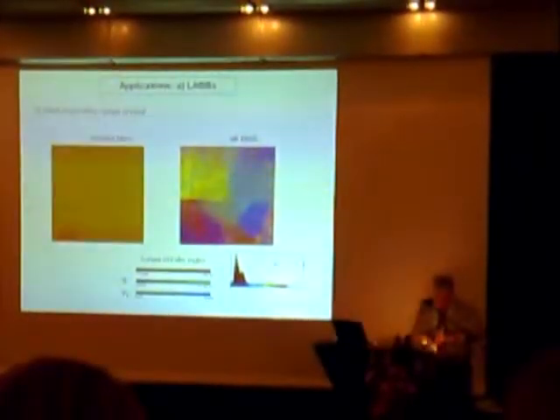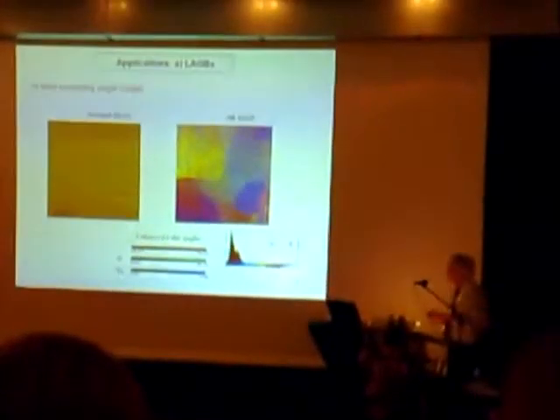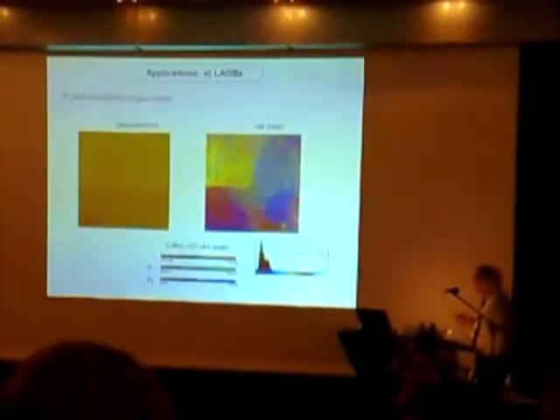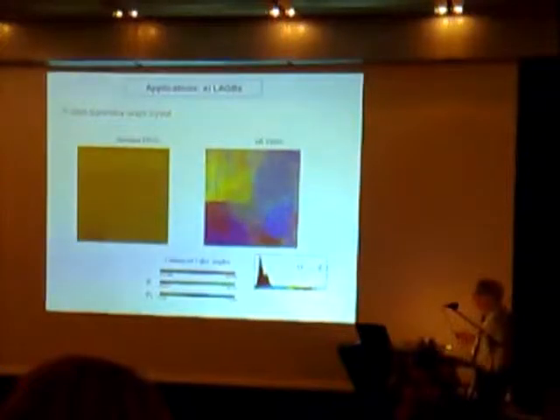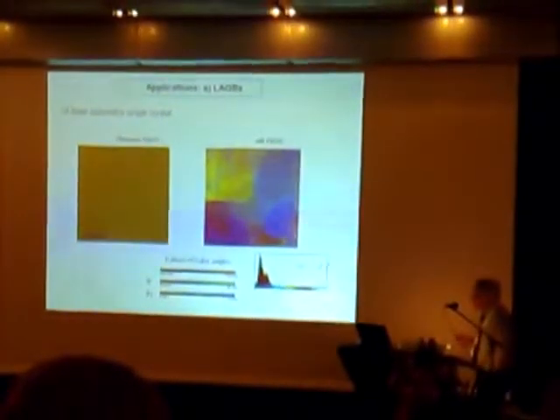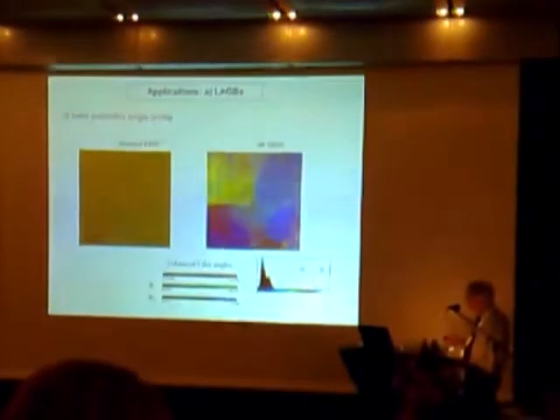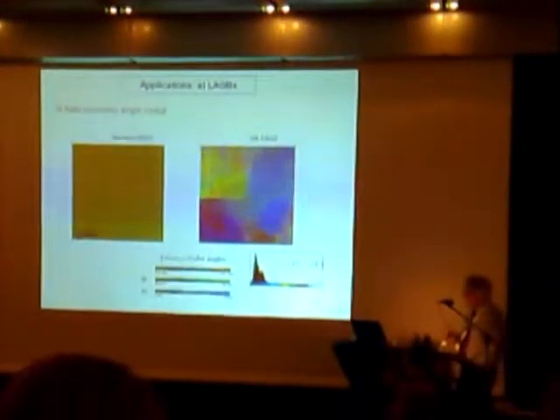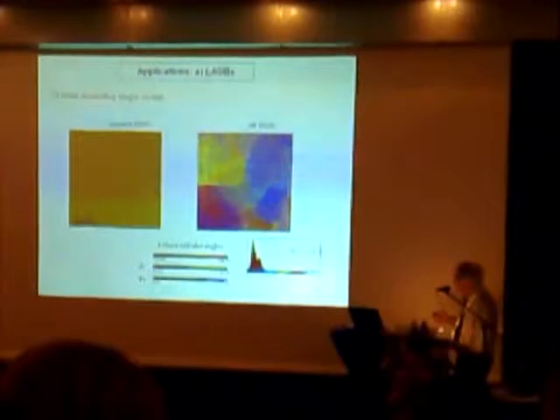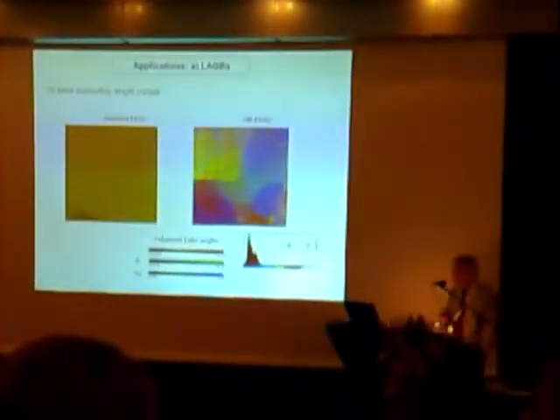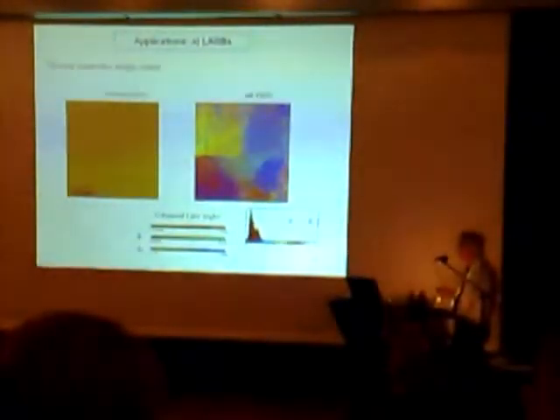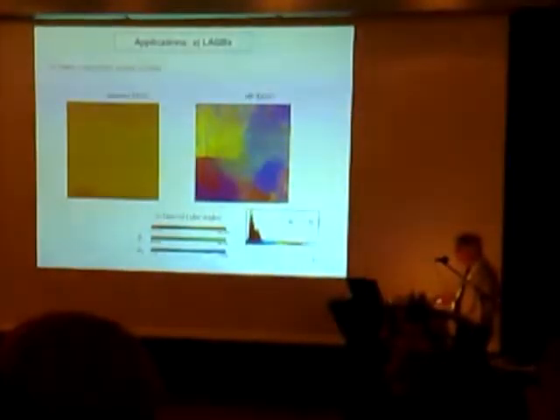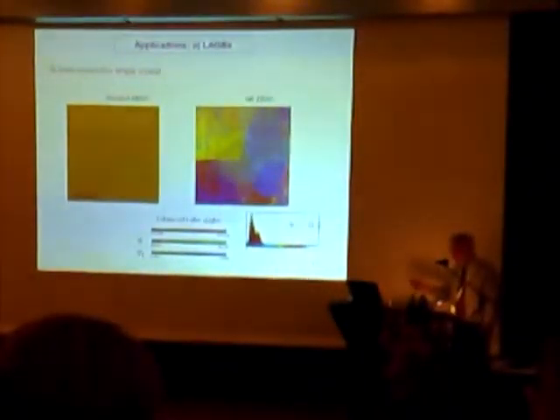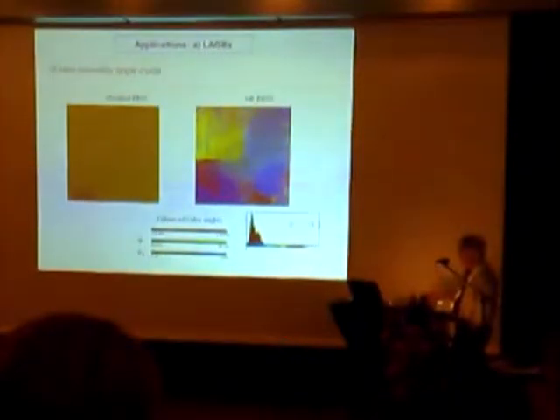And so I will just give you now a few examples of what you can do and how to correct for things. The first is looking at low angle boundaries. Here we're looking at a nickel-based superalloy single crystal. Of course it's a single crystal, so by standard EBSD you get nothing but the orientation. This is what you see in the Euler angle. If, for the same data set, for every pixel, you apply high resolution EBSD analysis, then this is the map of orientations you get. And the Euler angles, if you look here, show a small variation, 0.2, 0.3 degrees. So it's a very small scale, we're looking at variations of tenths of degrees.